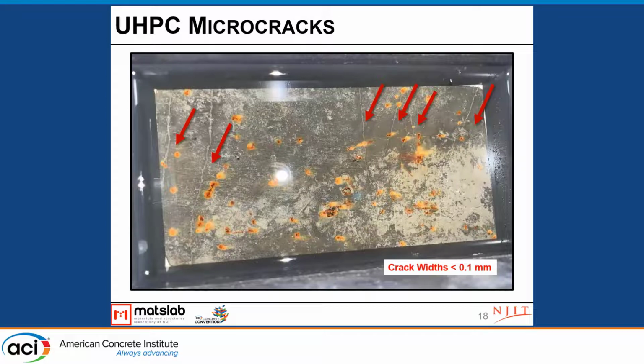The interesting thing is that we loaded the UHPC beams up to 80% and nothing happened that we could see with the eyes. So we continued loading until we got some cracks, up to 90%, sometimes 95%, to see cracks that we can see with the eye. And the main difference, as you can see, is the cracking behavior. As we discussed first, we have micro-cracking behavior instead of one big crack in the middle.